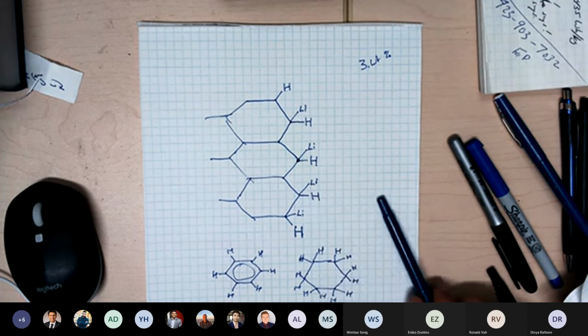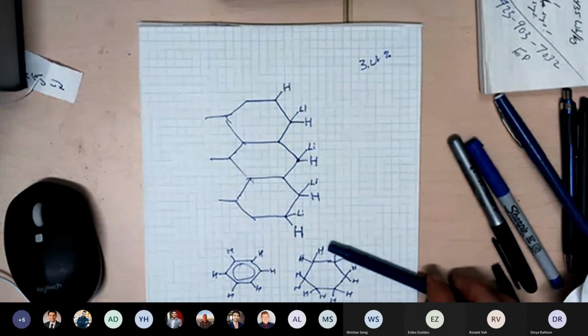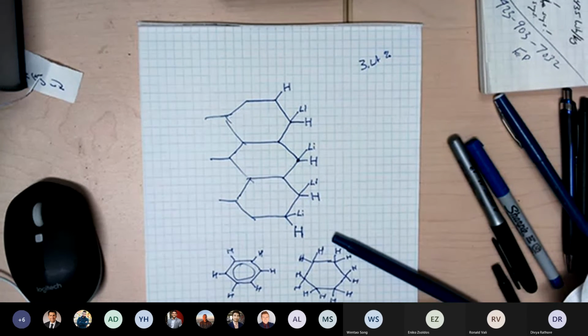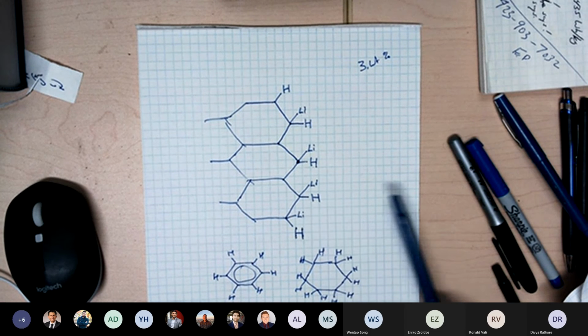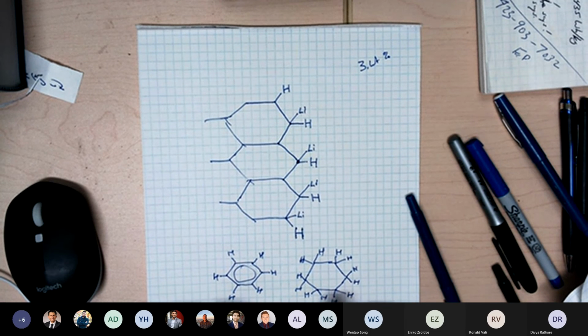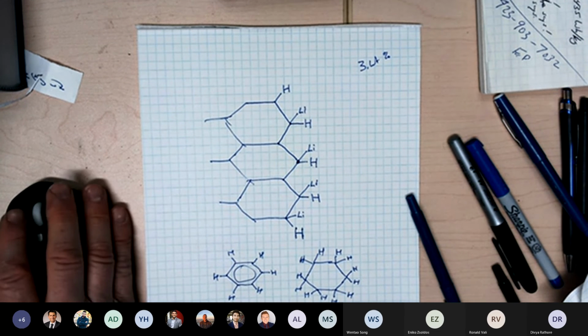Why? Because you start with silicon-silicon bonds. In silicon, you end with no silicon-silicon bonds left in the material when the lithium's fully reactive. Here, the host changes. You have graphite with regular intercalation. The graphene layers don't change at all. The lithium goes in between, and you have reversible intercalation and deintercalation.